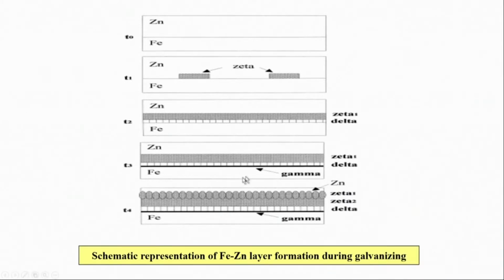Now, this is the slide which shows you the schematic of the intermetallic formation with time. When time is very short, if you just keep iron in molten zinc, you will find there is no intermetallic, but gradually there is formation of intermetallic, and the first intermetallic which forms is the zeta phase. Then as you go on increasing the time, you will find there is delta phase formation, zeta transforms to zeta prime or zeta 1 phase, and then gradually there is formation of zeta 1 and zeta 2 and gamma phase also at the interface.